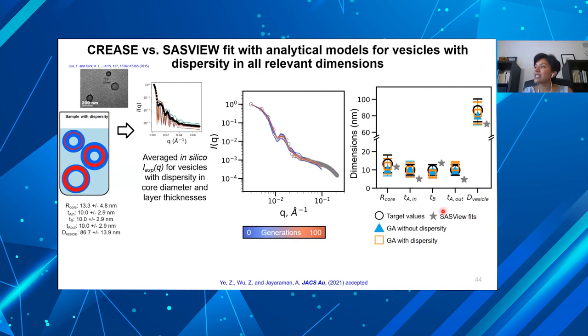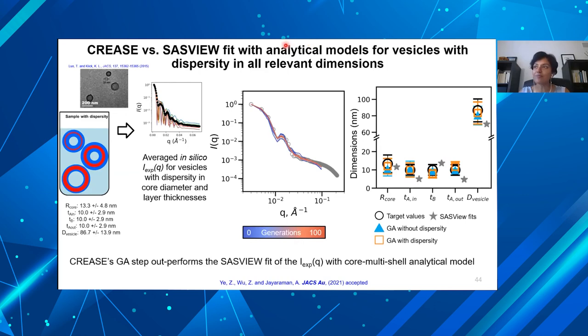But if we now see the SasView fits with a good analytical model for vesicles, it does a poor job in many of the dimensions. And so in this particular case, dispersed vesicles is handled much better by CREASE than if you had a good analytical model for vesicles and used a nice fitting package that many scatterers use.